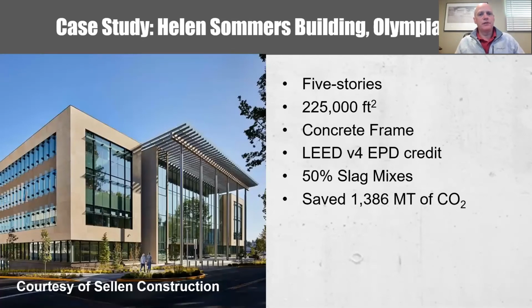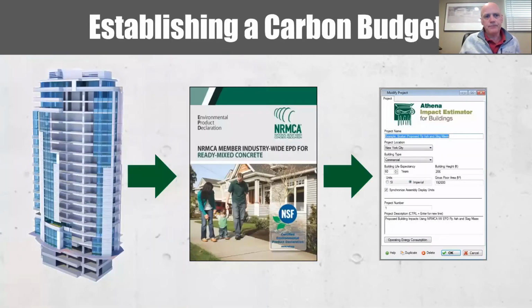Here's an example of a project in Olympia, Washington, the Helen Sommers building, where it was a 5-story, 225,000 square foot building, concrete frame construction, LEED V4. EPD credit is what they went for. And in the building, they used a significant amount of mixtures that have 50% slag mixes. And in total, it saved over 1,386 metric tons of CO2. Just by looking at very efficient mixes for this concrete building.